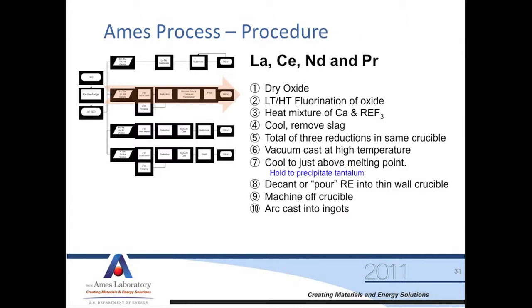But the process is very similar. We dry the oxide, but we do one more step that we don't do in the first group, which is we fluorinate the oxide. Mix that with calcium, heat it, remove the slag. We'll do 3 reductions, one on top of the other. We'll see that. Then we vacuum cast at high temperature.